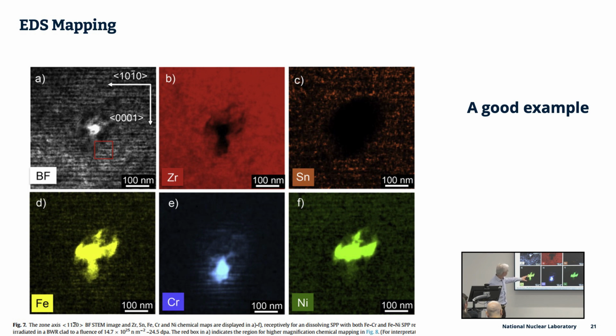The iron which has dissolved out of the SPP reprecipitates on these loops, and you can see that in a halo effect around the original SPP. I think chrome appears to do the same thing. You can see these lines of enriched chromium, and I can't remember the story now, but I think the tin is enriched between the loops, isn't it? Shown in the map on the top right there. And this is a really good example of the illustrative power of mapping. Doing something like this with point analyses, it doesn't have the same impact at all.